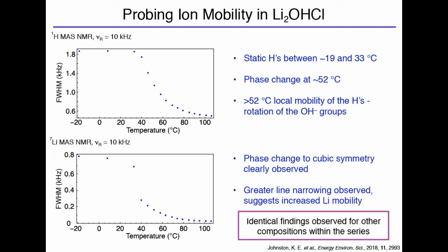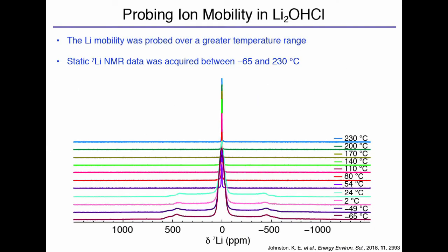the proton. Now, we looked at the whole series, so not just Li2OHCl, but changing the lithium and the proton content, and we see exactly the same across the series. So this is not an anomaly, this is happening consistently. So obviously, the lithium is the thing that's going to move if this was to become a solid electrolyte. So we really want to know how that lithium is moving within our material.